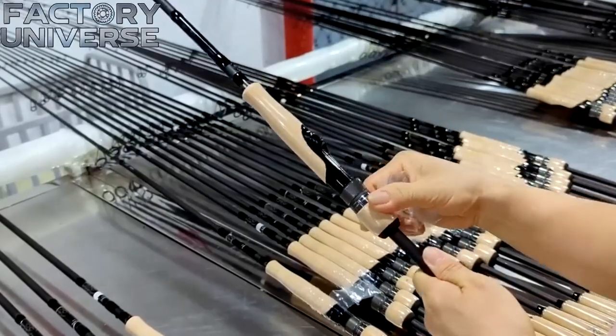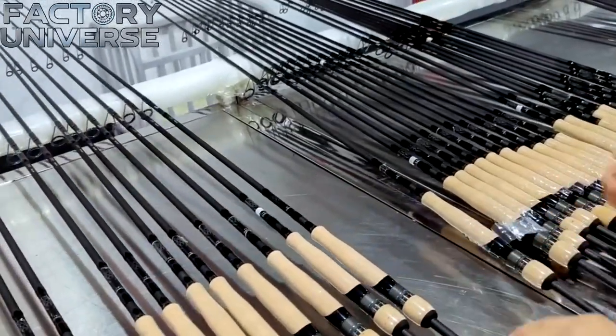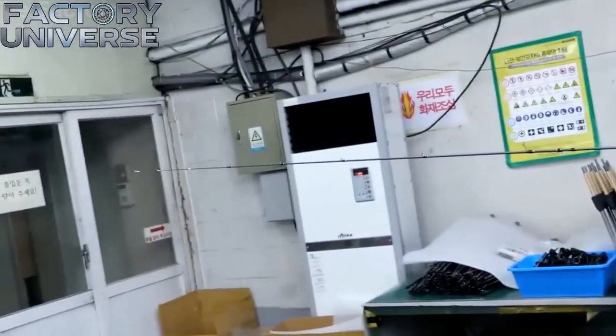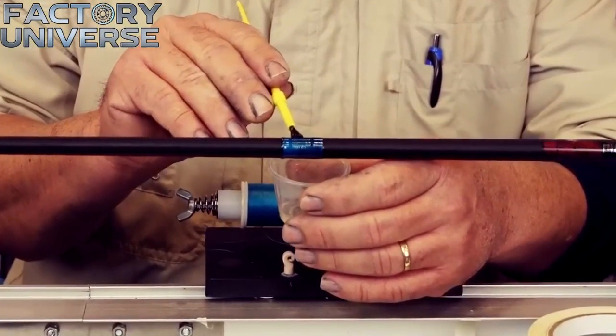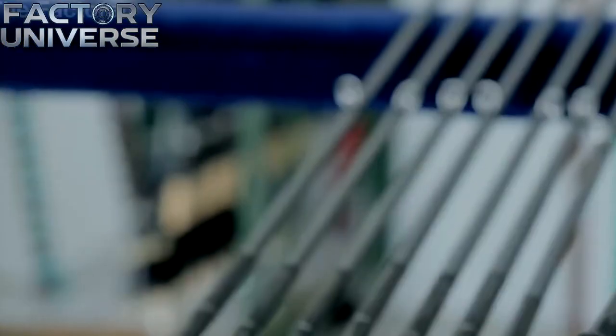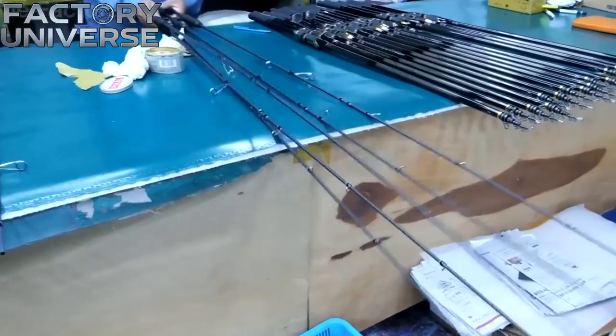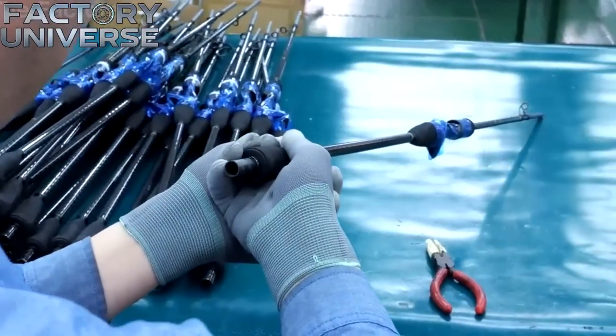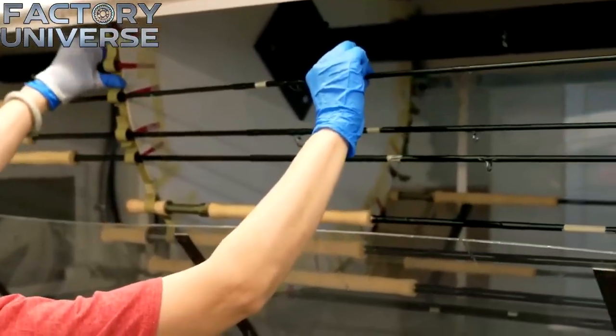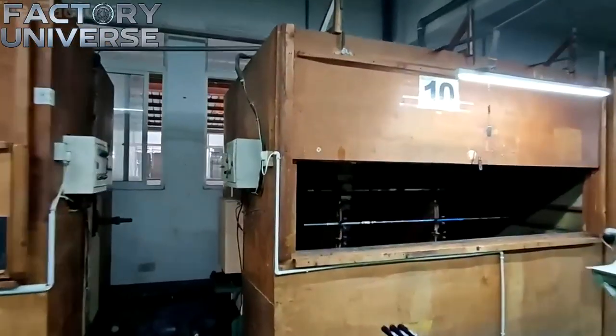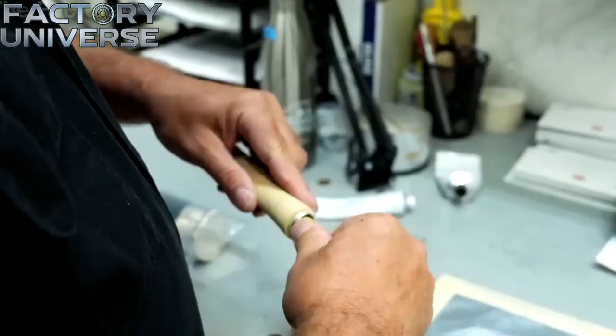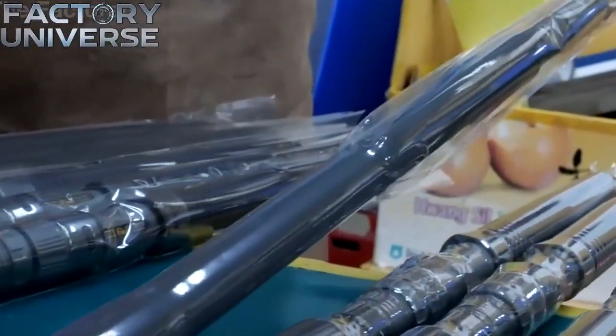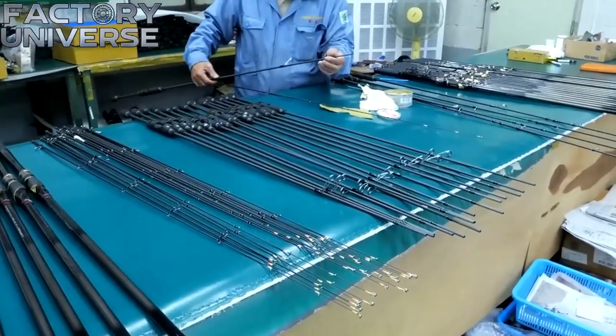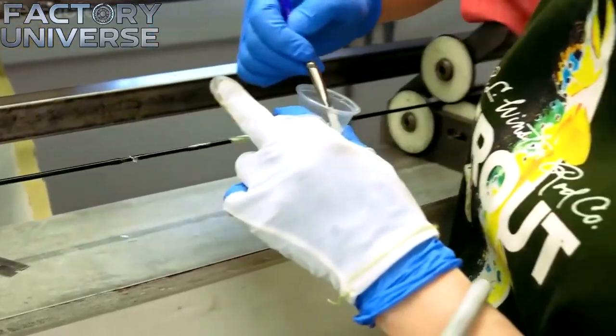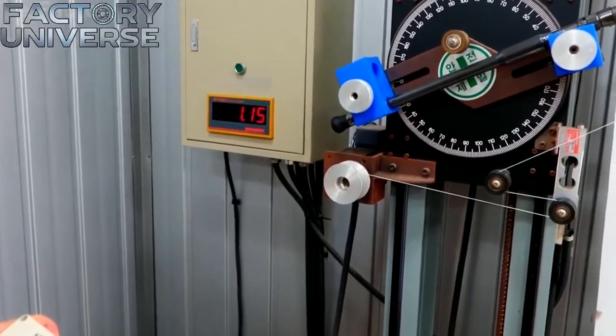Next, the rod is placed onto a rotating rack or a turning drum. This continuous motion allows the liquid epoxy to level itself perfectly around each guide under the influence of gravity and rotation. The rods then pass through a flow of hot air or an ultraviolet curing chamber. These two elements, heat and ultraviolet exposure, serve to partially cure the epoxy and stabilize the wraps before a second application. A final glossy coat of epoxy is then brushed on to create a thick, durable, and protective surface. In a single day, the factory consumes thousands of ounces of finishing material during this specific phase. Dozens of rods rotate simultaneously on each drying rack, ensuring the finish cures with absolute uniformity.